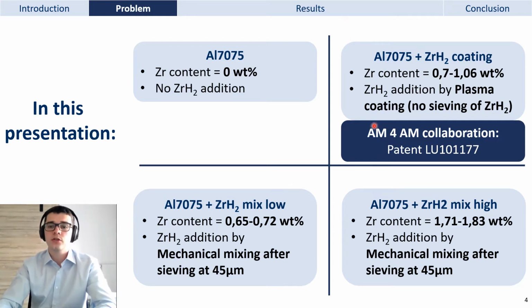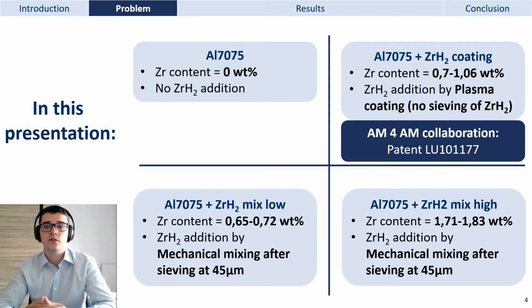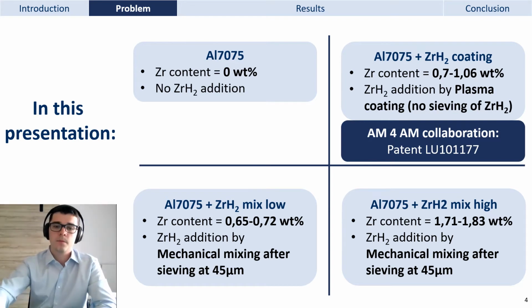For more information about the plasma coating, you can refer to the patent that is mentioned on the slide. For the coating, the zirconium hydride powder was not sieved. It has a lower zirconium content than the high zirconium content mix and could have more zirconium than the low content one. So you must keep that in mind for the comparison that will be made during the presentation.